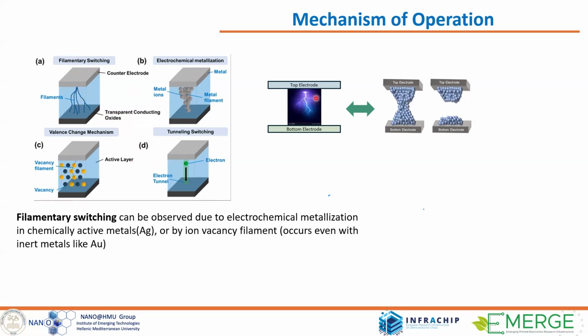The second type of switching is what we call interface switching. Here we don't have any filament, but we have accumulation of charges, carriers and ions at the interfaces that form a Schottky barrier. So when the Schottky barrier is high, we have a high resistance state. When you reverse the polarity of the voltage, you minimize this Schottky barrier, so you jump to a low resistance state.